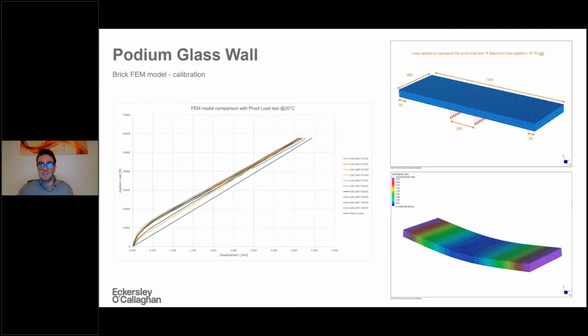For people who don't know, in Hong Kong the composite action of glass is still not given for granted. Therefore, every time you want to use composite action in a glass panel, you need to do a 4-point bending test. And even if the 4-point bending test returns 100% composite action, you're still limited to a value of 70% of composite action to be used.